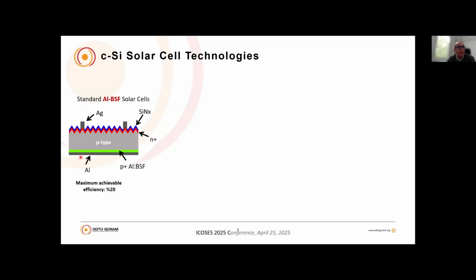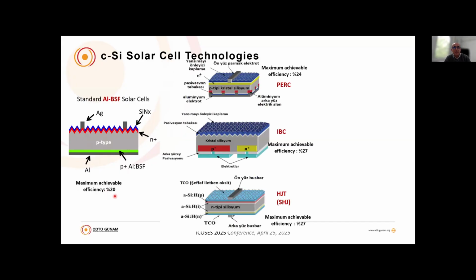On the backside, we have aluminum coverage fully on the backside. During the processing, some of the aluminum diffuses into the substrate, creating a P+ layer on the backside, which provides the electric field effect, which is useful to reduce the recombination on the backside. So the maximum achievable efficiency was about 20% with this structure. But later on, of course, new technologies have been developed. The most successful one was the PERC solar cell. In this case, the backside of the solar cell is no longer in full contact with the aluminum metal layer.